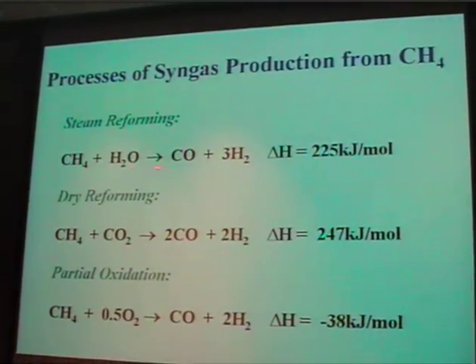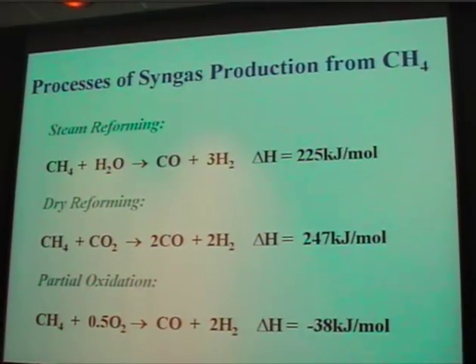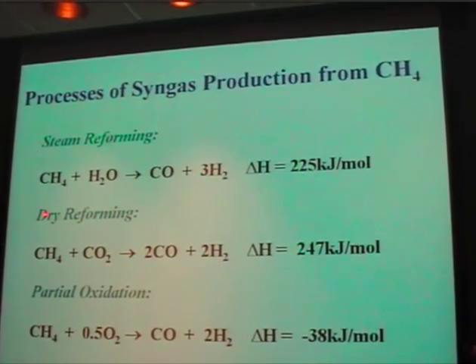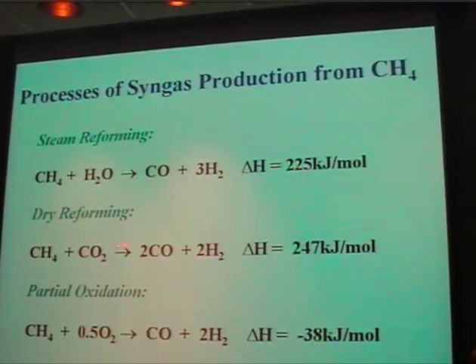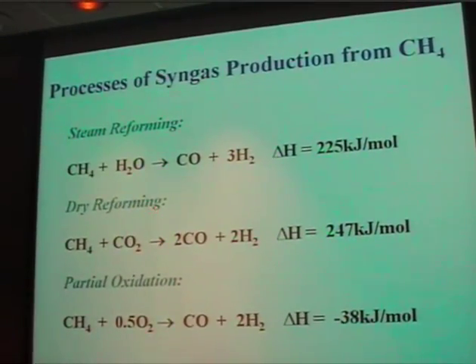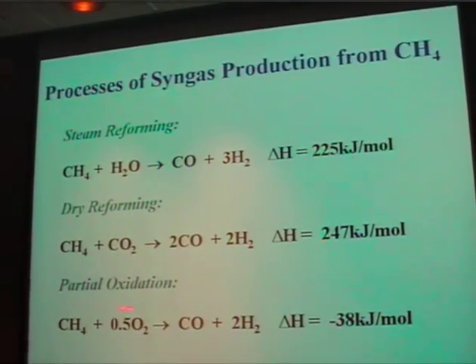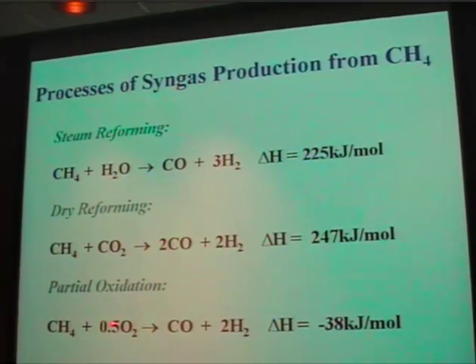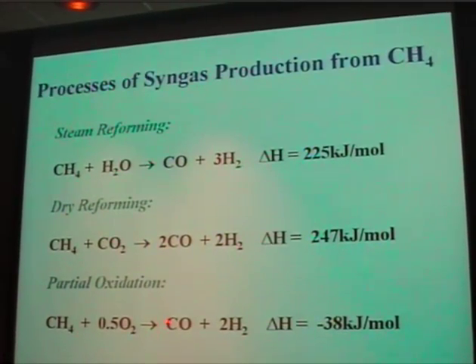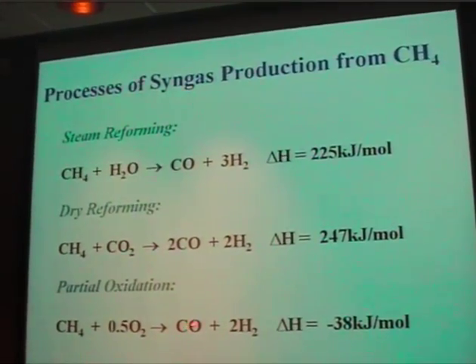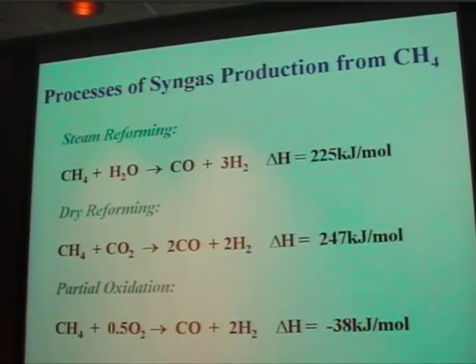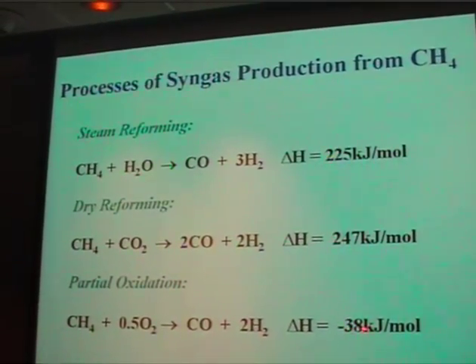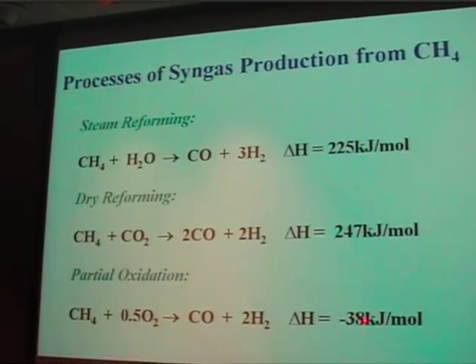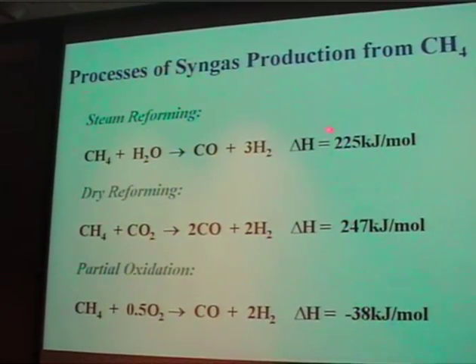Most of the commercial industry uses steam reforming, and you can also reform methane with CO2. They call it dry reforming. And as I mentioned, our approach was to do partial oxidation. This looked very attractive. You got the preferred ratio of CO to hydrogen. Also, it has the advantage of being slightly exothermic, whereas the other two approaches are endothermic.